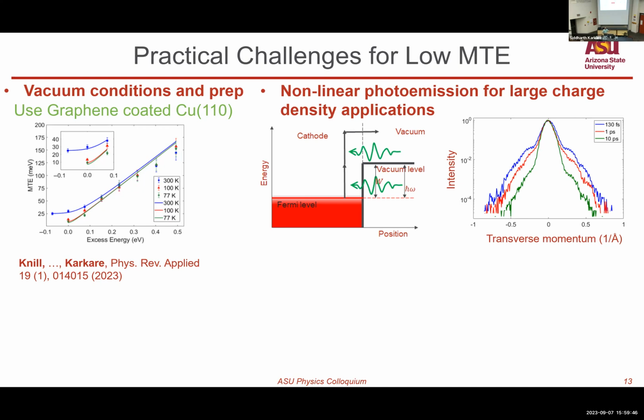So to get a large charge density, we need to smack it with a very intense laser pulse. And that gives rise to nonlinear photoemissions. An electron absorbs 2 photons and comes out with a very large excess energy. And for the first time, we characterized this effect experimentally, and we were able to map out the transverse momentum distributions from intense laser pulses with different pulse lengths. And we can see all these nonlinear photoemission peaks in the transverse momentum distribution.